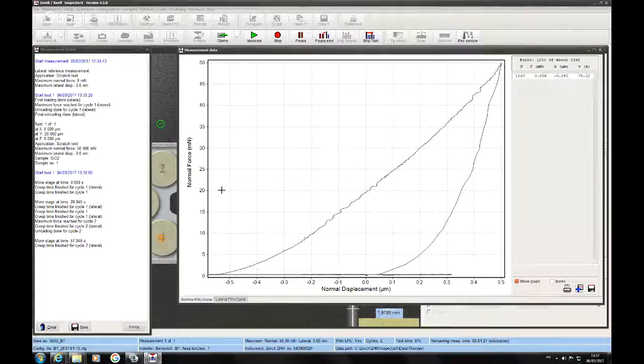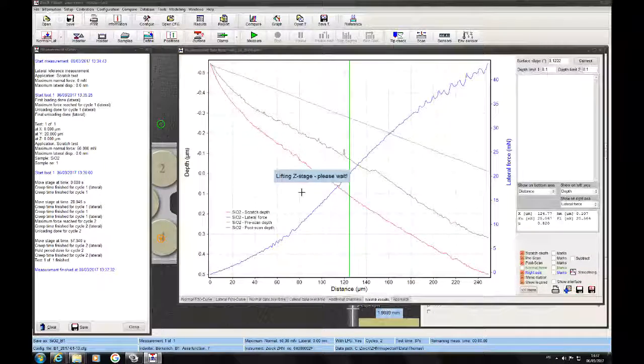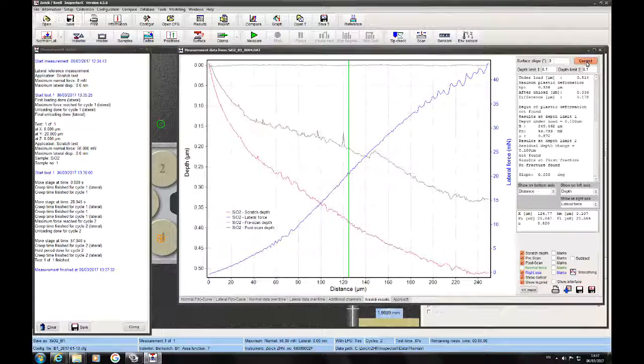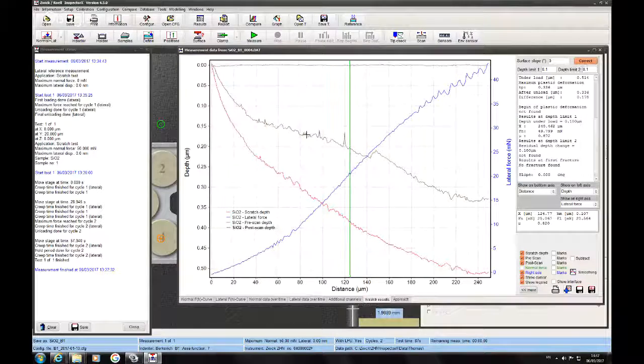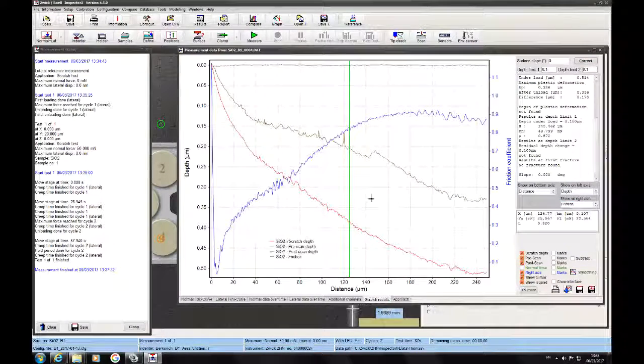And when this is ready, it will show the scratch results, because this curve here is difficult to understand, because it's the slope and the indentation depth in the same curve. Now you see the scratch results. You see the slope of the pre-scan, the gray line, and you see the calculated slope is only 0.12 degree. We can correct this. You see the brown line is the plastic deformation, and the red line is plastic and elastic deformation. We see the blue line as the lateral force. We can convert this to friction. So we have a relatively high friction due to the strong plastic deformation.